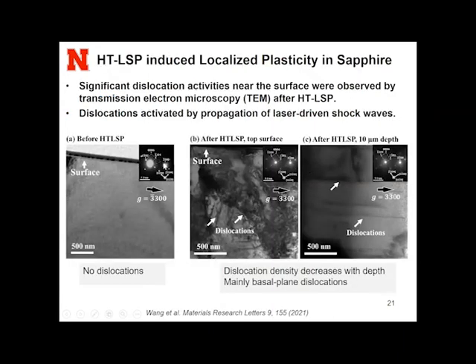Okay, for the microstructure, here shows a cross-section microstructure analysis by TEM. Before the high temperature laser shock peening, there's no dislocation, and after laser shock peening, you can see here we generate a very high density of dislocation, and the dislocation density decreases with depth, but you can still see a lot of dislocation.